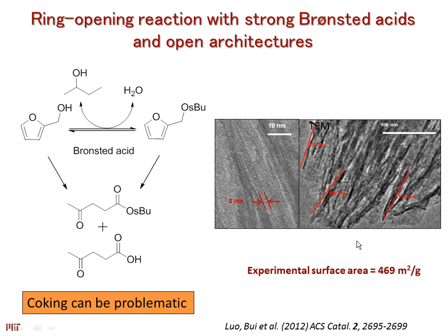And this actually is not a trivial reaction. Making these levulinate derivatives either in water or in an alcoholic solvent creates a lot of byproducts, and a lot of it are consecutive reactions. And what we found is that usually you want to operate with a strong Bronsted acid, but you need something that has a good stability and open architecture, and that's when we went to what I call our molecular engineering toolkit, and tried to create these zeolites. This is mimicking the work, for example, by Ryu in Korea, where you can start making some of these zeolite nanosheets, which are, I hope you can see them from far back, where you have pretty much a unit cell-wide MFI catalyst that has a lot of open sites with still quite a bit of strong Bronsted acidity.